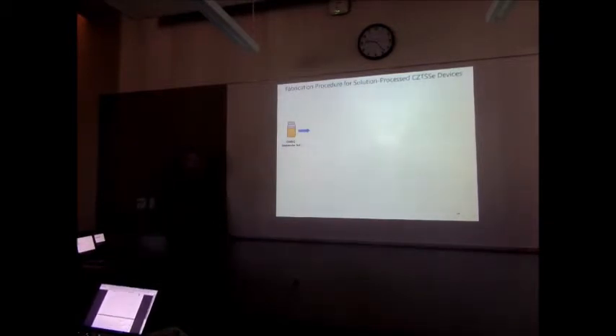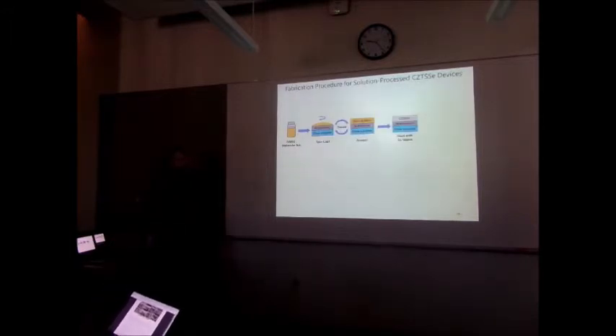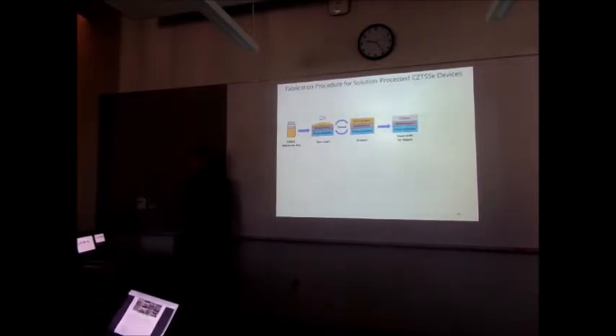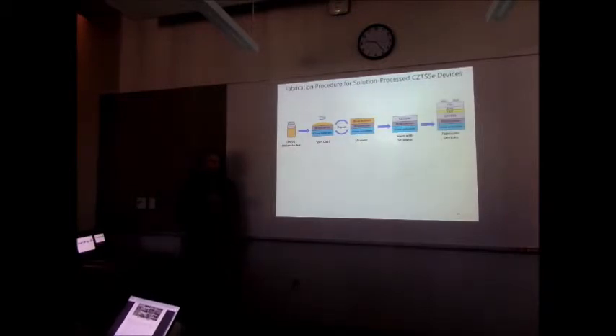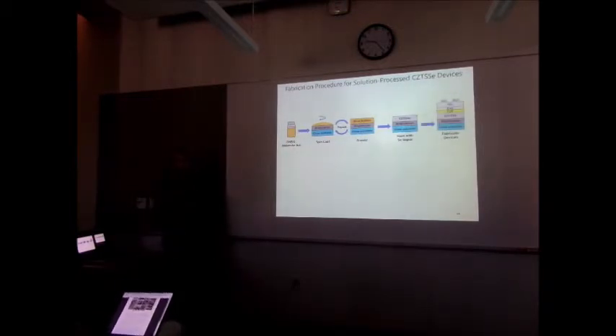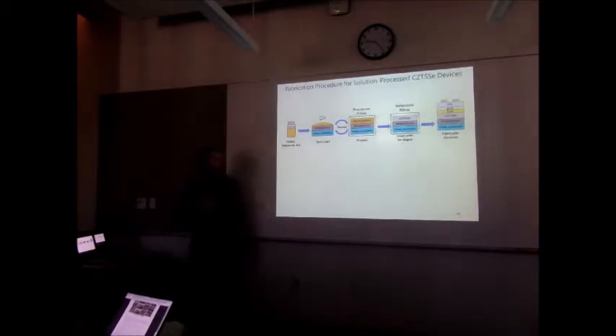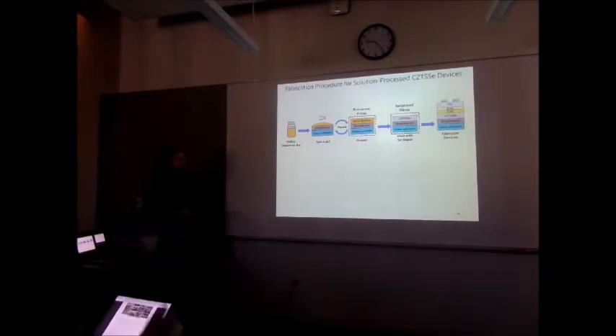So to do that, I want to give a brief overview of how we make these solution process CZTS films. We start with this DMSO molecular ink. We spin coat it and anneal it, and then we selenize it, where we heat it with selenium vapor. And then we fabricate devices with a number of other steps that I won't get into here, but are very important to get right.